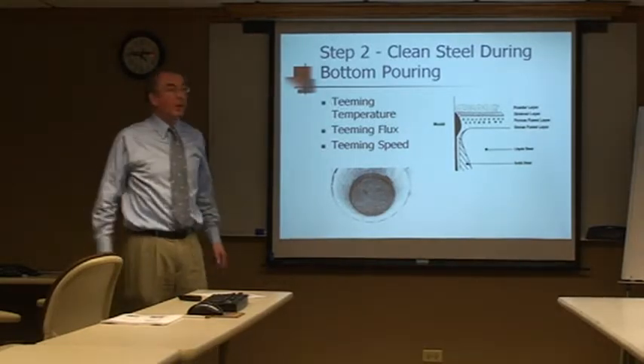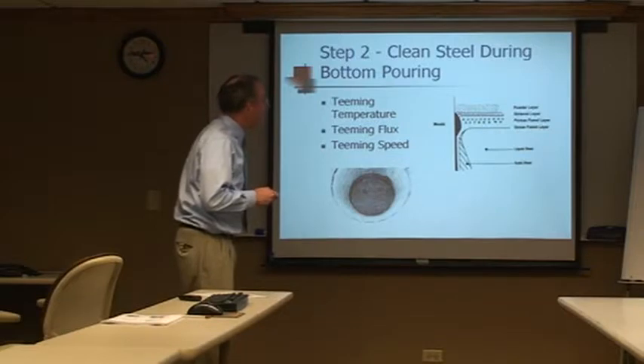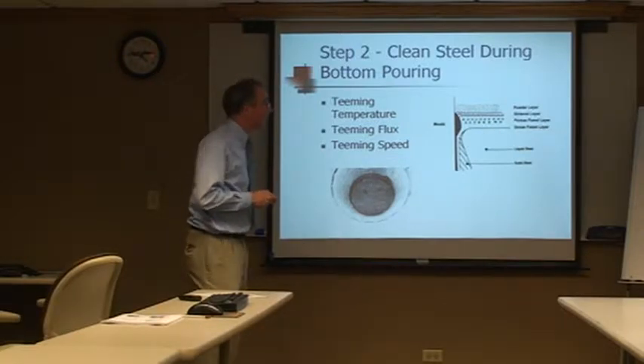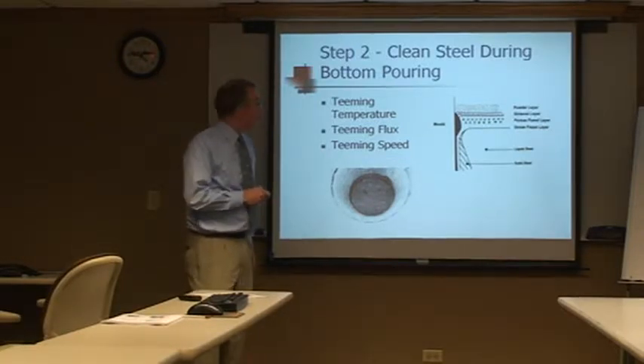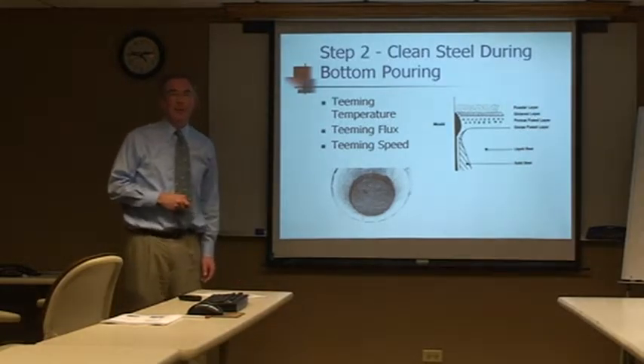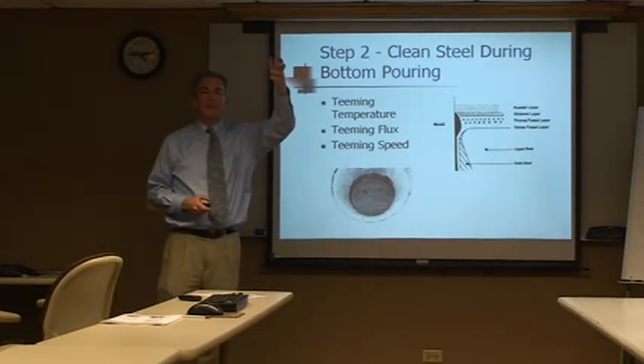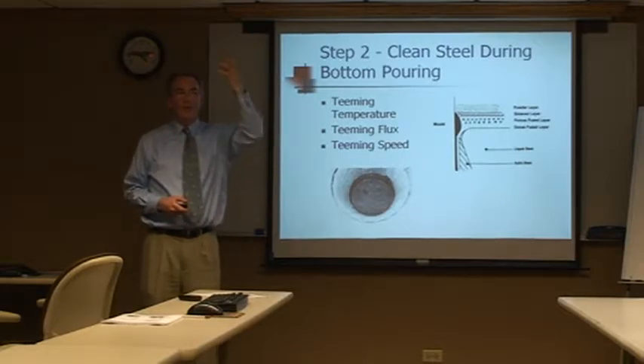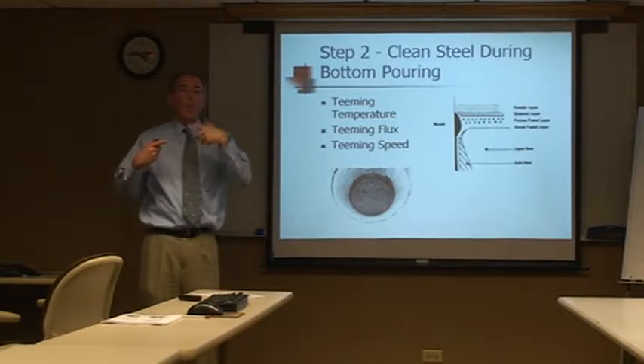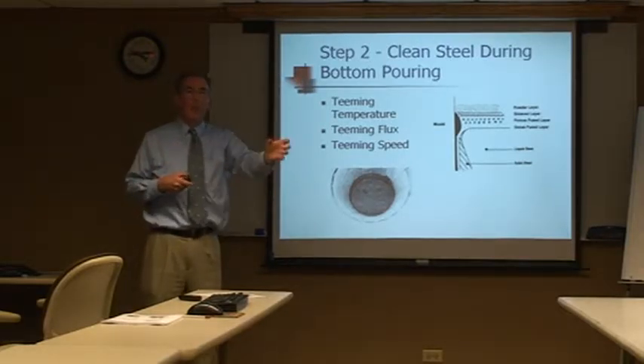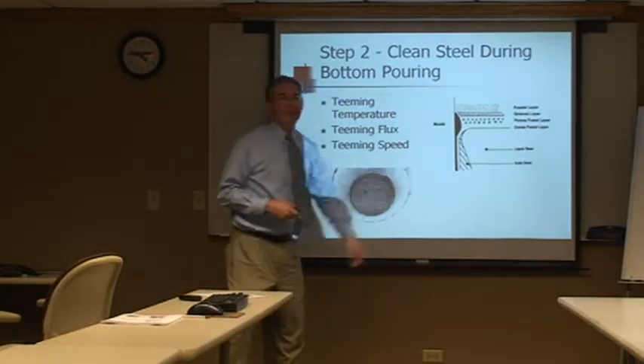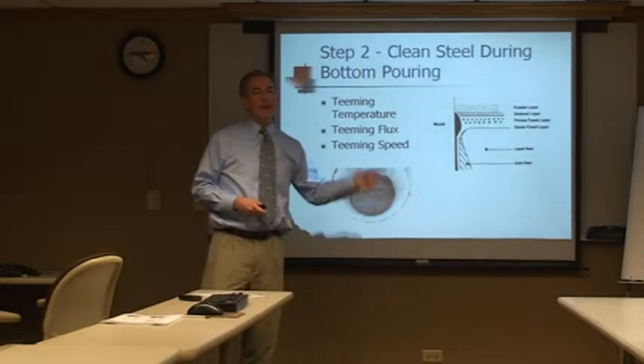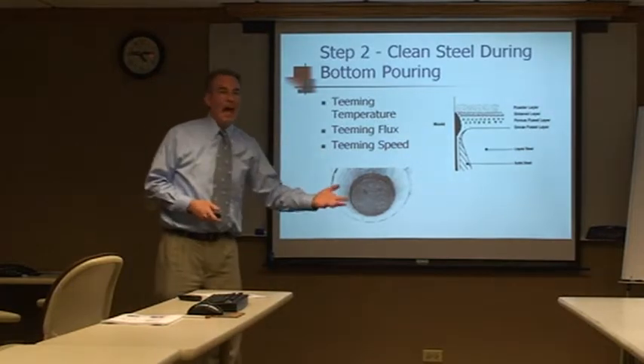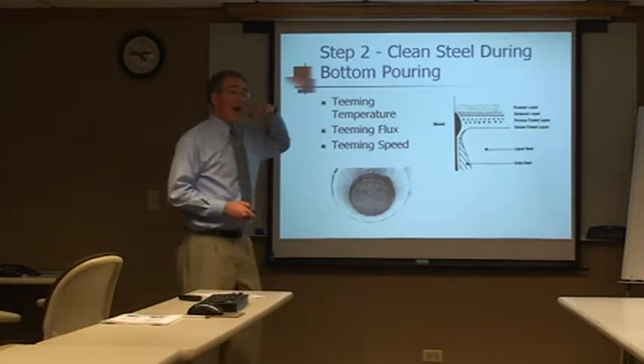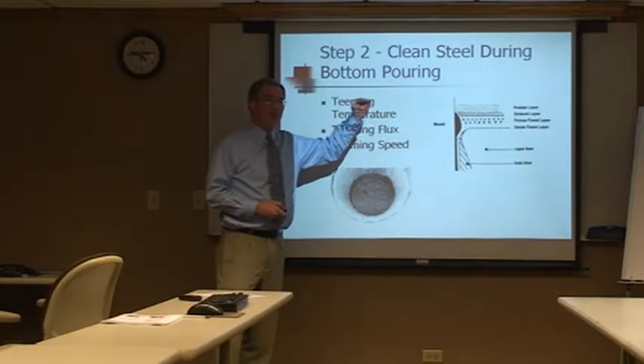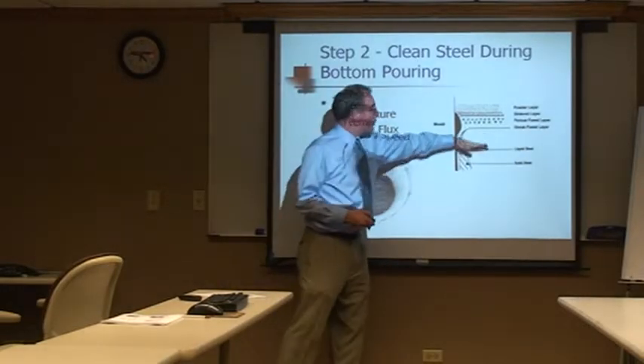That's the good part. The scary part is we do not want to mix this teeming flux with this liquid steel. So we have to control our teeming speed. On the ladle, there's load cells, and that load cell records the weight. And we're able to convert that weight over time into a pouring rate. So as we're pouring, we can say we're pouring 1 ton per minute, 2 tons per minute, 1.5 tons per minute. So we will actually cap how fast we pour the steel to make sure we don't pour too fast.